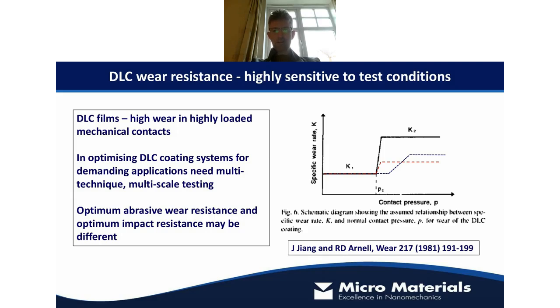This on the right is a schematic by Derek Arnell, right back sort of 40 years ago now, showing essentially low wear rate for DLCs in low pressure contacts, and then an abrupt transition to a high wear rate regime. So what I've dashed there, just adapting his figure, is a red and a blue line, indicating that we might be able to develop multi-layer coating compositions or doped coating compositions that don't have a severe failure mechanism compared to the normal undoped DLCs, and that could be attractive in applications where these things are subjected to occasional high pressure contacts.